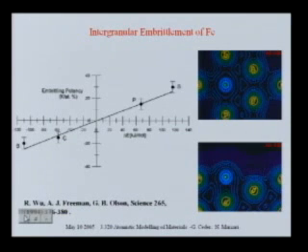I think it probably has to do with, well, first of all, boron is smaller. There's definitely a size effect. Boron and carbon, these two are much smaller than these two. But there's another effect, I think, which is that these tend to have much more bonding potency. So in a grain boundary, they have higher coordination. So they gain a lot more from covalent bonding than these two. These two don't gain as much from being coordinated by iron atoms. I think that's the gist of it as I remember, but that's exactly what that paper is about.